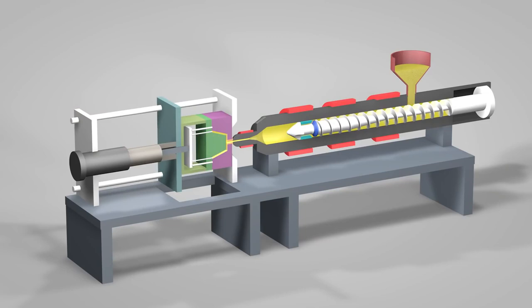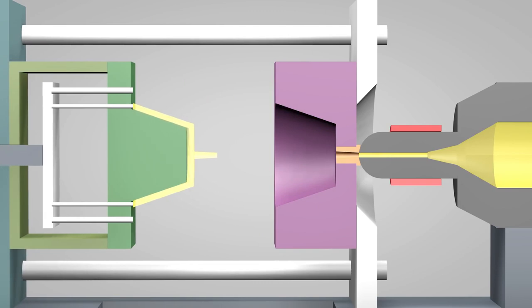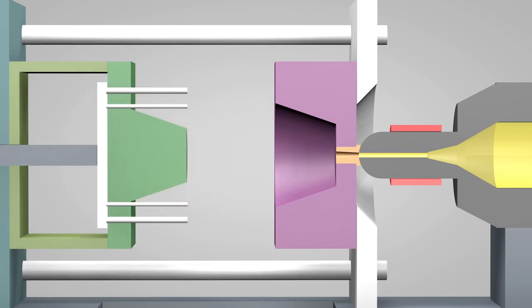After the injected part solidifies, the mold opens. As the mold opens, the volume increases without introducing air, which creates tremendous suction that holds the mold together. So at first the mold slowly opens several millimeters to allow air to rush in and break the vacuum, and then the mold quickly opens the rest of the way so the part can be removed. These precision machine steel molds can cost hundreds of thousands of dollars.